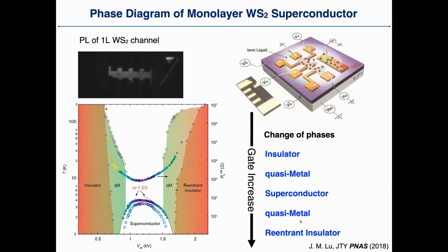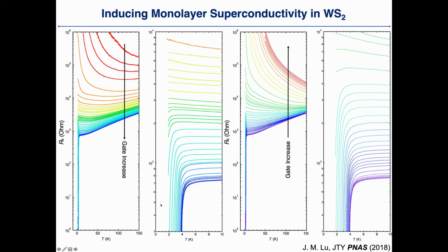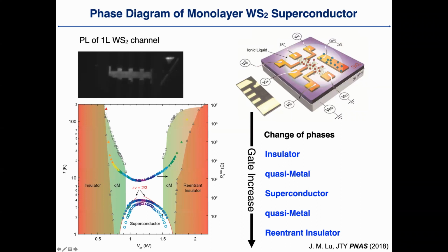We go to the monolayer limit, and this is the PL image of the channel of the monolayer. And then we can see this phenomenon more obviously. So we have a dome-like shape, and before the dome and after the dome, we always have a metallic phase and an insulating phase. After the dome, we have this metallic phase and this insulating phase, which we call re-entrant insulating, which is very counterintuitive, because normally we believe if we apply a gate voltage, we pump carriers into the system, and the system becomes conductive, and with more carriers, with more gating, it can be a superconductor, but it can never become insulating again.